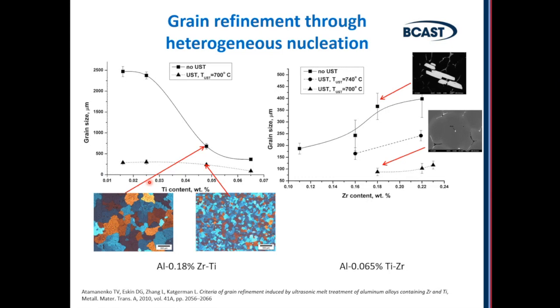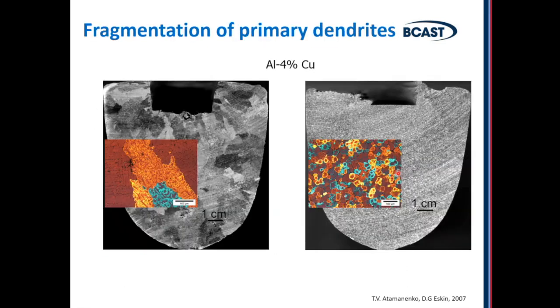So you can refine primary intermetallics by activation of substrates and refine them to such a size that these intermetallics start to be nuclei for aluminum. This particular example is aluminum 3 zirconium phase, which we refine from this coarse intermetallic to this very fine intermetallic, which then by its size and chemical or structural properties serves as a very good nuclei for aluminum, and you can achieve very good grain refinement by this kind of two-stage mechanism.